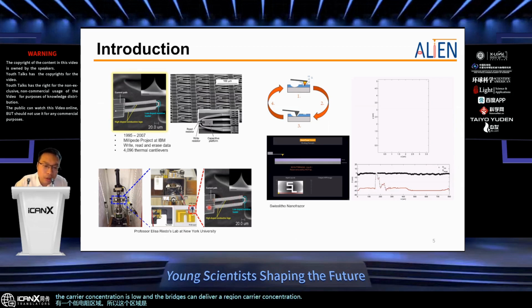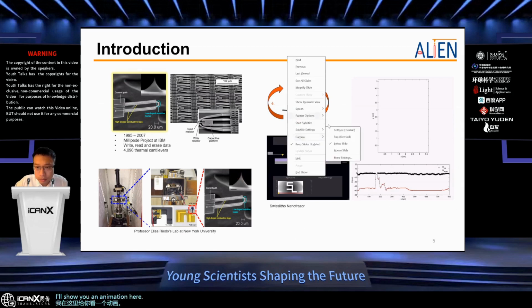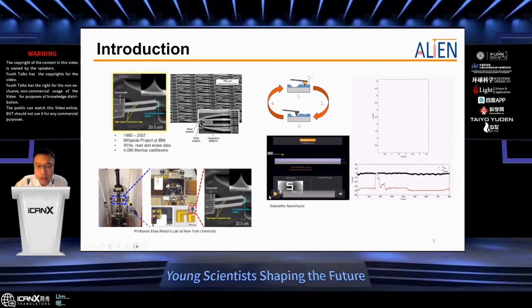So if we flow a current or apply a voltage, we can have Joule heating accumulated at the apex of the cantilever, and this heat can transmit into the tip apex, so that the tip can be heated and burn the polymers. I'll show you an animation here. So as you can see, the tip is burning some polymers and creating structures, and during the retrace, the tip is measuring the contour, the topography, at the same time.